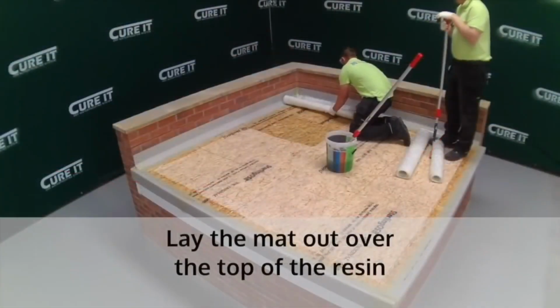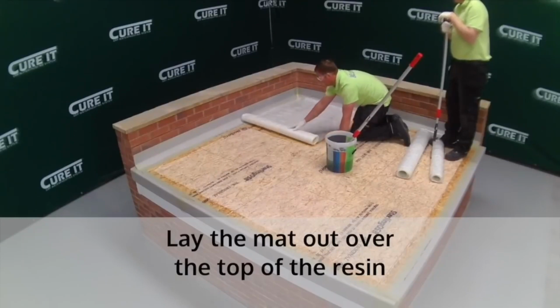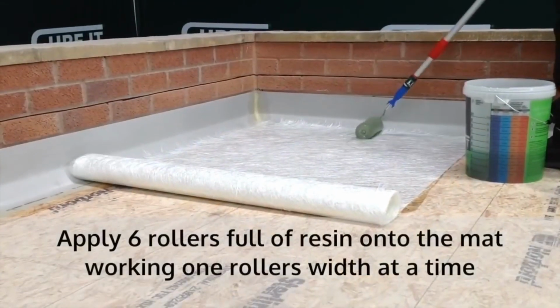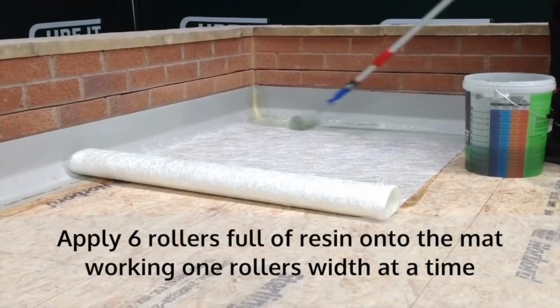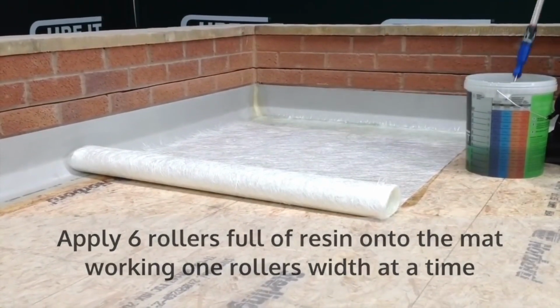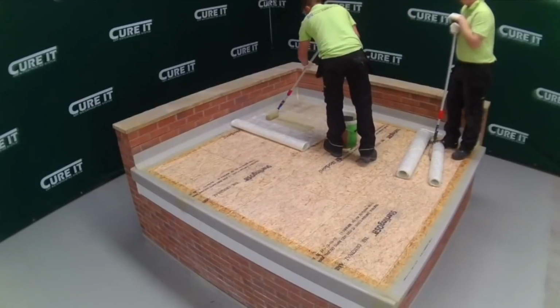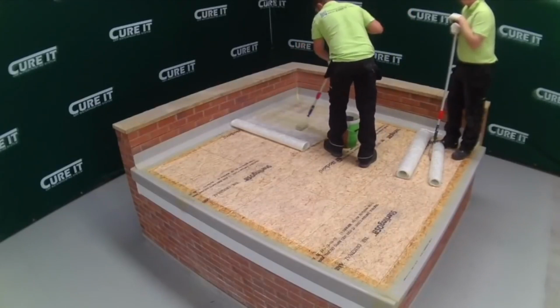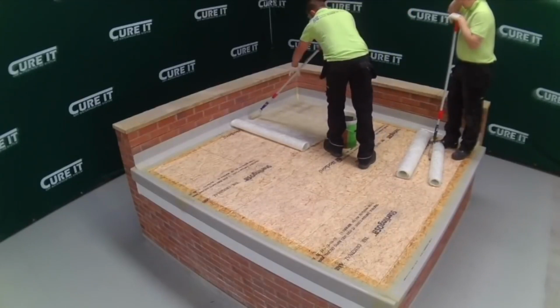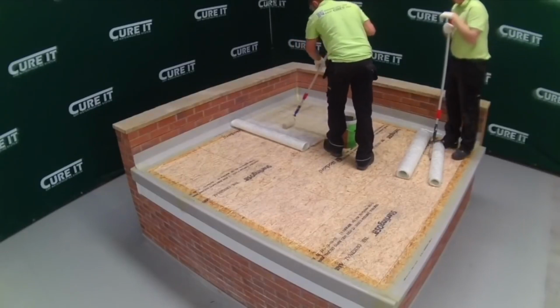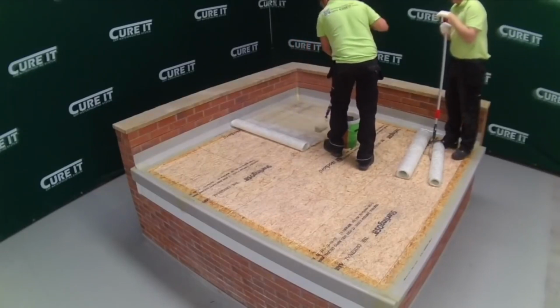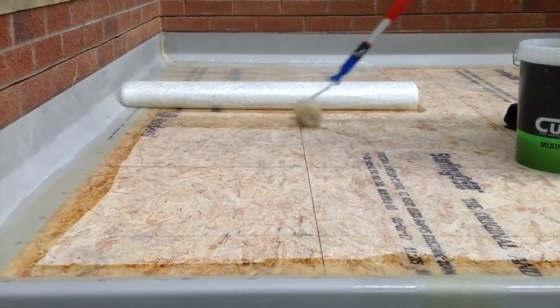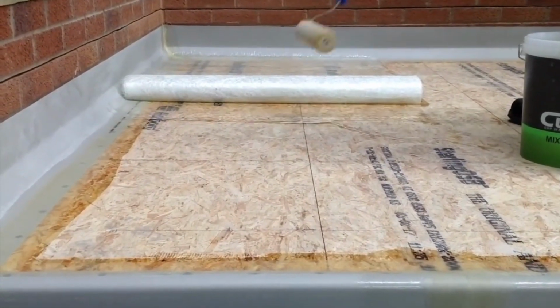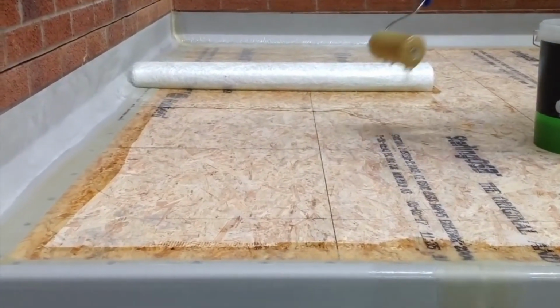Take the first piece of reinforcement mat that was measured earlier and roll it out over the resin. Apply 6 rollers full of resin over the reinforcement mat, working 1 roller's width at a time. Each roller full of resin should be placed into the middle of the mat and applied, rolling the resin away from the middle and then back towards the other end to cover the strip. It's important to ensure the matting is completely saturated with resin at this stage.